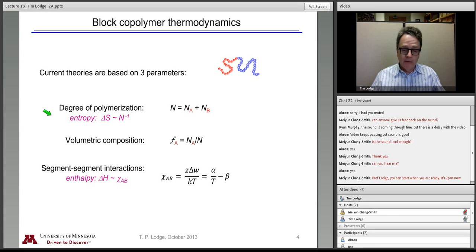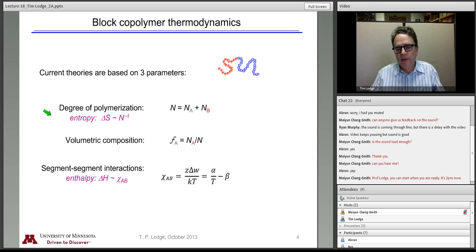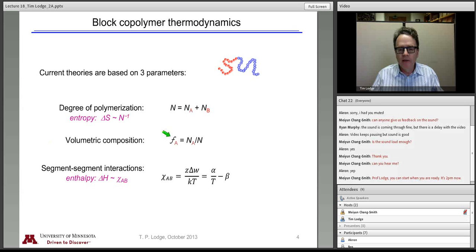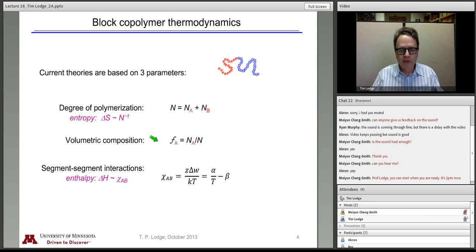The entropy in a block polymer system is proportional to 1/N. This was also true in Flory-Huggins theory — the free energy of mixing had the ideal entropy of mixing inversely proportional to degree of polymerization — but the entropy we're talking about here is different, though it still has the same scaling on molecular weight. Instead of the volume fraction of a component in a mixture, we now talk about the volume fraction of the first block, which we'll call script F sub A. Because we have defined these degrees of polymerization on a common reference volume, the volumetric composition is just this fraction of degree of polymerization.